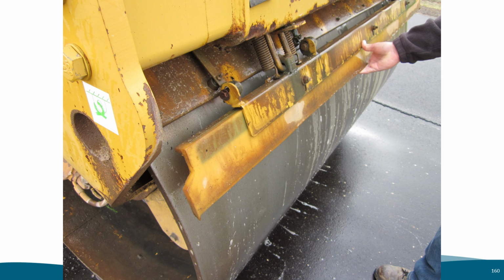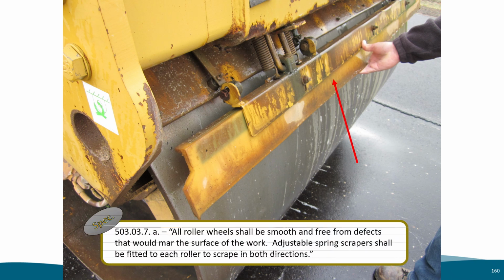Here is a close-up photo showing the roller drum and the scrapers. As written in the standard specification, all roller wheels shall be smooth and free from defects that would mar the surface of the work. Adjustable spring scrapers shall be fitted to each roller to scrape in both directions. This picture also shows the drum scraper. Be sure to check the condition of the rollers before use.